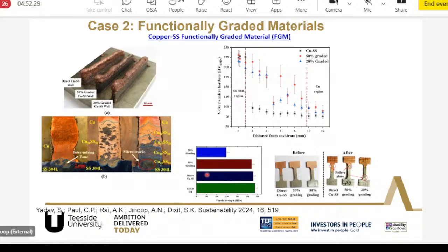And we could see that the mechanical properties of 50% graded structures are at par with the copper and the direct copper-SS, while 20% grading has got more defects, mainly because of the more thermal cycling it has undertaken. We have more cracks in this particular case.